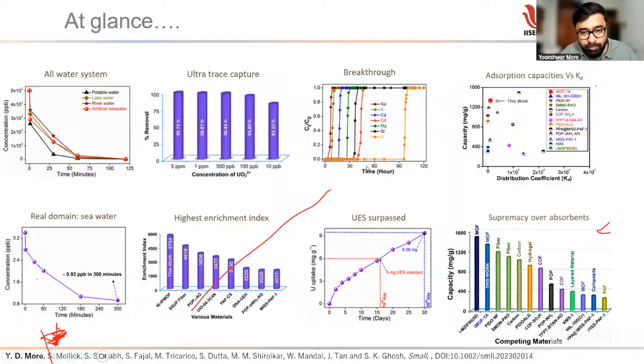So in the breakthrough, if uranium is retained, it will come last, because it is interacting with the column, that is a MOF bed, and it should be retained by the MOF, and other cations will come under the force of flux. So you can see the sodium comes first, then potassium, then calcium, then magnesium, then strontium, and then cadmium. But uranium comes last. It's because the uranium is held by the MOF assembly, and that's why the breakthrough is successful. This experiment is always essential for the commercial application.